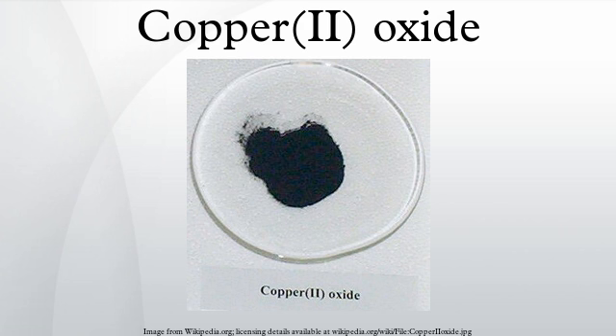Crystal structure. Copper(II) oxide belongs to the monoclinic crystal system, with a crystallographic point group of 2/m or C2h. The space group of its unit cell is C2/c, and its lattice parameters are a = 4.6837(5), b = 3.4226(5), c = 5.1288(6), α = 90°, β = 99.54(1)°, γ = 90°. The copper atom is coordinated by 4 oxygen atoms in an approximately square planar configuration.